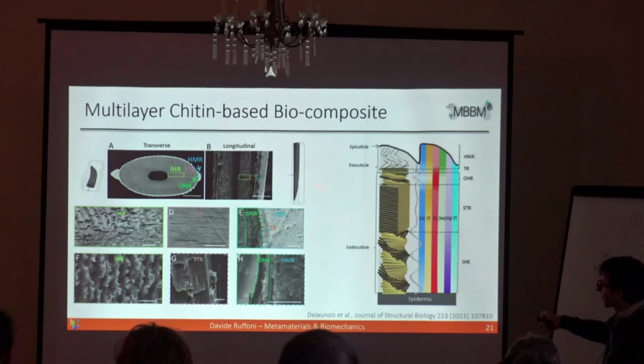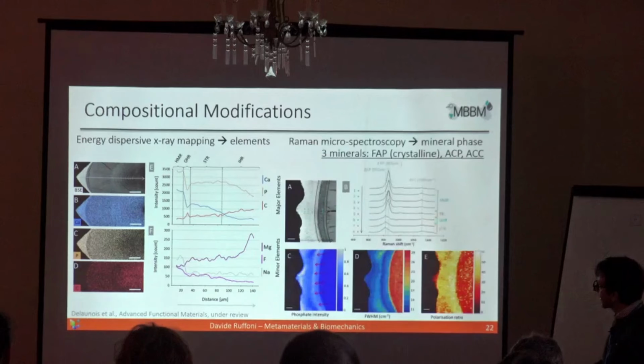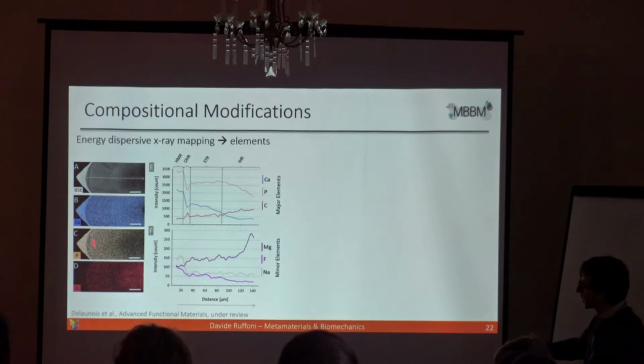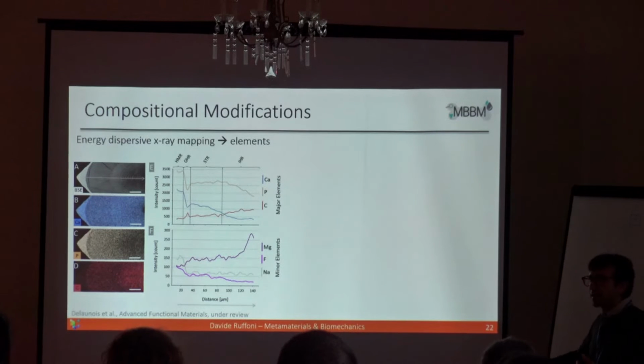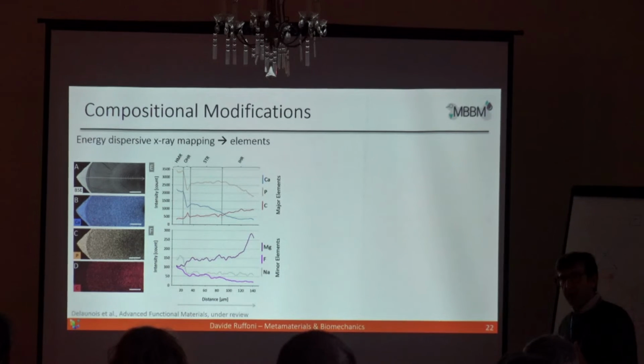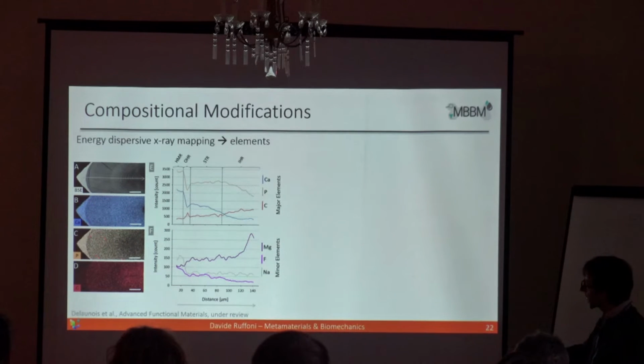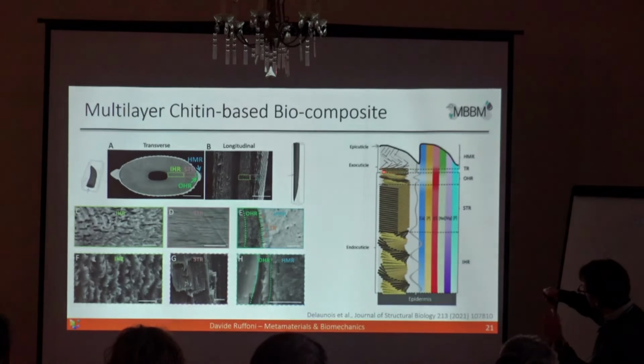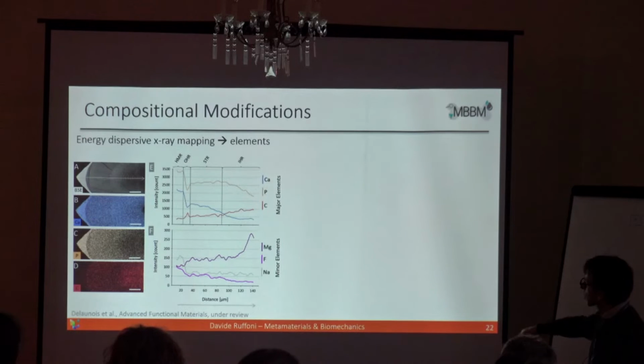So this is one first finding. Okay, it's a multi-layer material. In terms of element composition, this is not so surprising. Of course, what you should know for biological material is that they mainly use very simple chemical elements, in contrast to engineering materials, and here we see only calcium, phosphorus, carbon, for example, as major elements. And we see that in the outer, highly mineralized layer, there is a high presence of phosphorus and calcium. Then there is a drop corresponding to this Bouligand interface, and then, okay, then it's not so interesting.